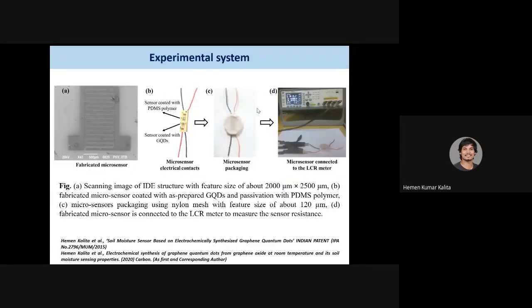Now, this is the scanning electron microscopy image of the IDE structure. You can see a very nice image of the IDE structure. This is diagram number A. The size of this electrode which we have fabricated is around 2000 micron by 2500 micron, length and breadth. And these are the finger-like structures where we deposited GQD. The electrical connections are done here in these two bigger pads. One will be connected to positive, the other to negative. So these two are used for the electrical connections.